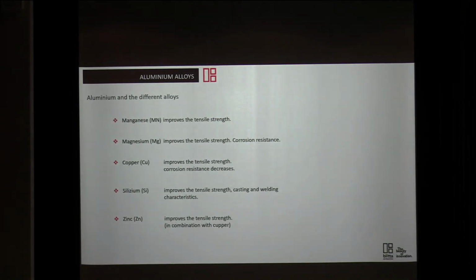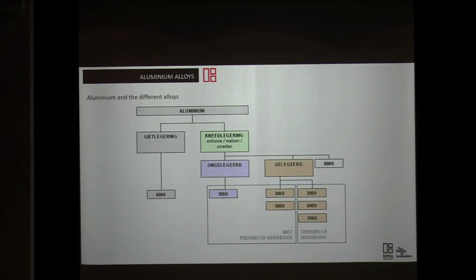As I said, the ingots are 100% aluminium. You have to alloy it to give it some properties. You make it a little bit stronger. You use manganese, magnesium, copper, silicium, and zinc to make the properties of the aluminium a little bit better. And for a total view, you have the cast alloys on the left. And then you have the green one, the forging alloys. That can be forging, that can be extrusion, that can be something else. Then you've got the non-alloyed and the alloyed.